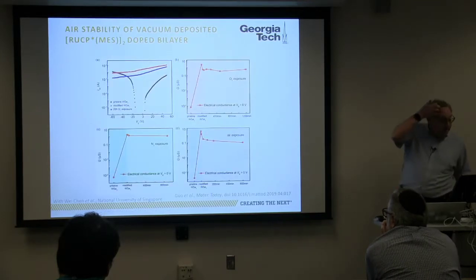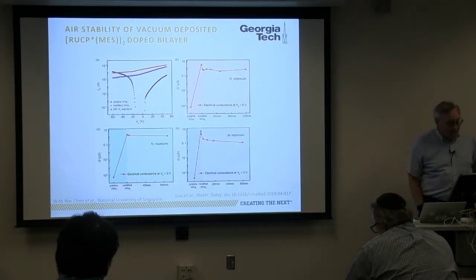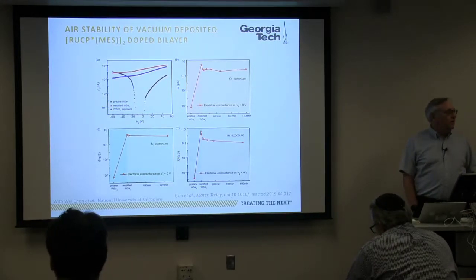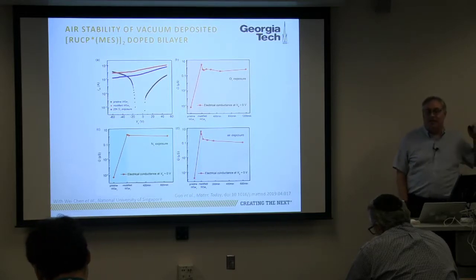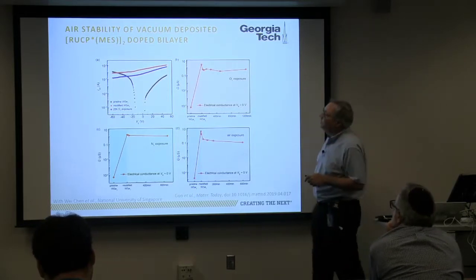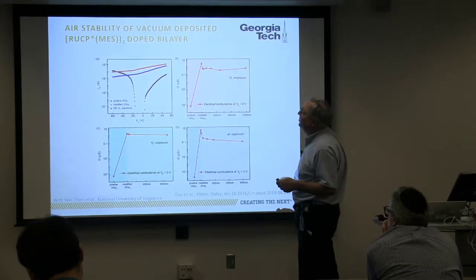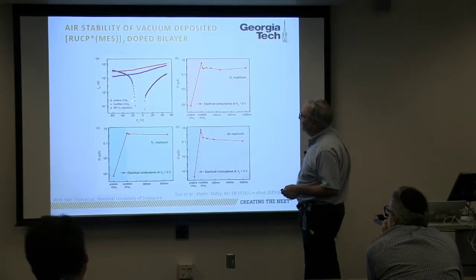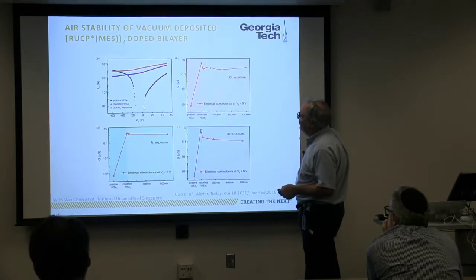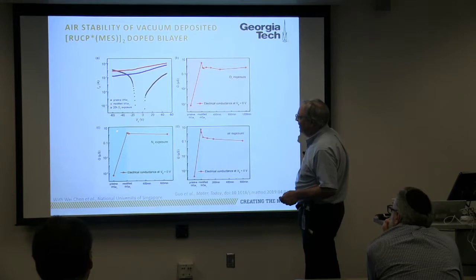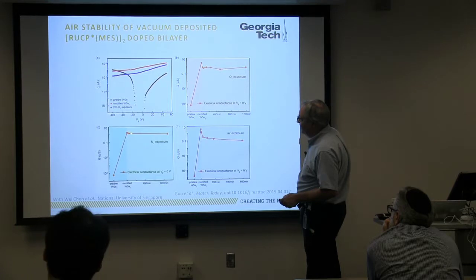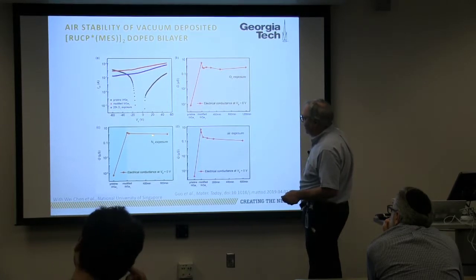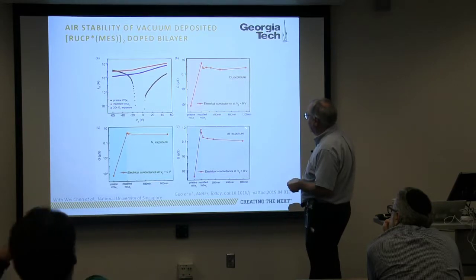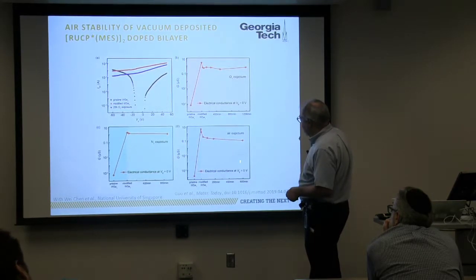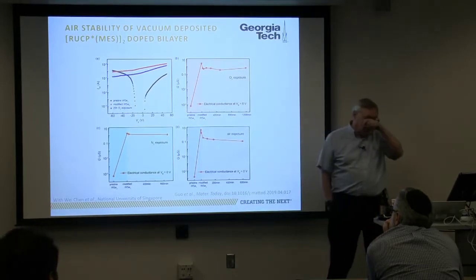Now here's another example that was done by Wei Chen and his colleagues with our dopants in Singapore. And now, instead of solution processing as we did with Eric, they vacuum deposited dopants on bilayers of these dichalcogenides. Okay, and here is the case with tungsten. And again, when they dope, they make these things pretty heavily n-channel doped. The conductance of the material goes up by 5 orders of magnitude. And the interesting thing is that when you expose this to either oxygen or air, even after 10 hours, basically you don't lose very much of the conductance.